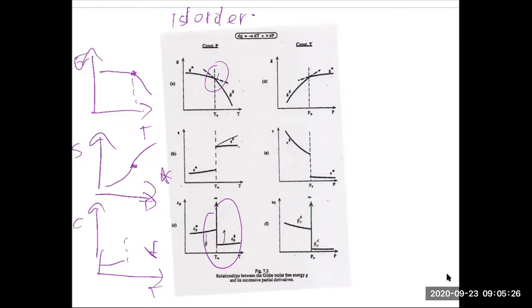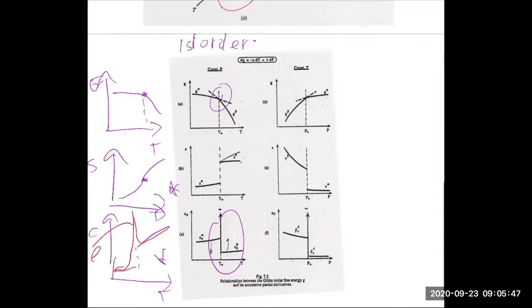You have a discontinuity in the heat capacity. If you actually accurately calculate or measure the heat capacity, it actually does something different. It has a logarithmic singularity and it would do this. And this singularity is logarithmic so that you don't integrate any infinity under it. So in reality, Ehrenfest wasn't quite complete. In reality, C goes to infinity at T second order.